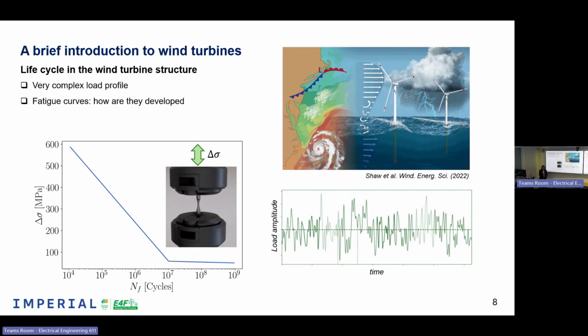They apply a cyclic load, define the number of cycles at which the specimen is breaking, and they build these kinds of curves called SN curves, where they relate the load with respect to the cycles. Now they apply a certain rule, the Palmgren-Miner rule or another similar one, where they quantify the damage of the structure. This damage is quantified by correlating the number of repetitions of loads that we have in a certain estimated profile with respect to the values estimated in the lab.